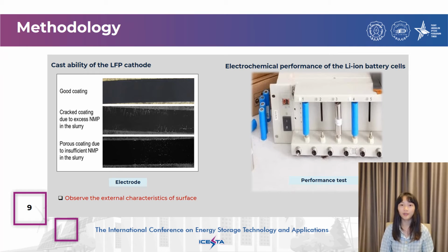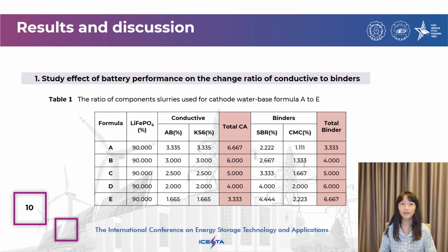Analysis and testing of the experiment will provide general information because of the limited test equipment in the laboratory. Testing of the LiFePO4 cathode is performed by a visual inspection of the external surface and noting the absorption of the coating. Testing of the lithium-ion battery cylinder cell for electrochemical performance is done with the battery testing machine, recording the following data about the charge, discharge, voltage, efficiency, and discharge specific capacity of each battery cell. Part 1 of the study is to demonstrate the effect on battery performance when the ratio of conductive and binder is altered. A total of 5 batteries with different ratios were tested.